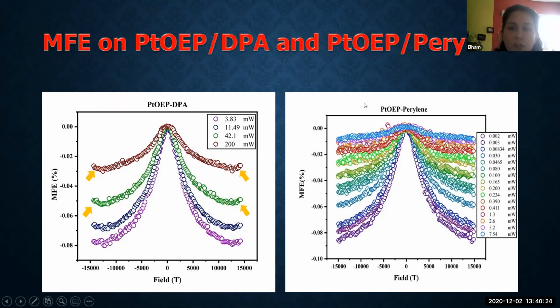And we did the same experiment in here because perylene has a high quantum yield, something like 96%. And the T2 channel is inaccessible in this case. It's about 4 electron volts, I think. So it's inaccessible. And as we expected to see, there is no jump at the end of the plots, but you see the same things happen to the delta PL during the measurements.